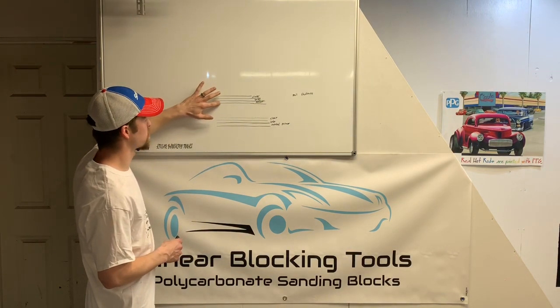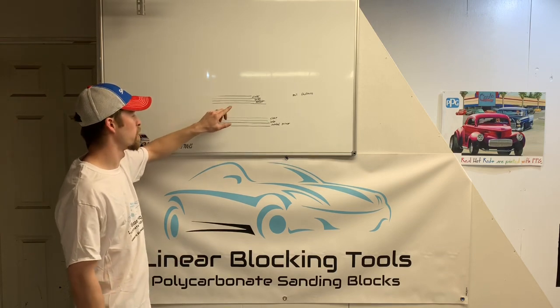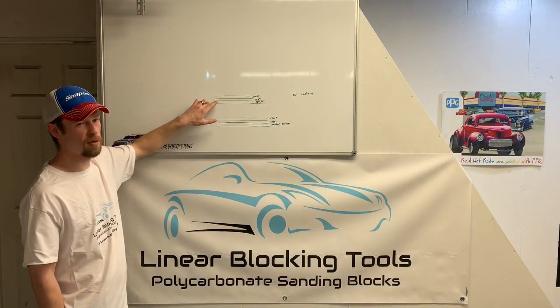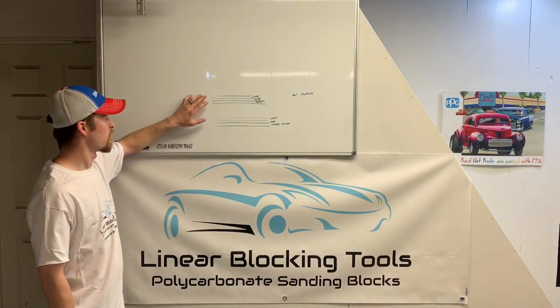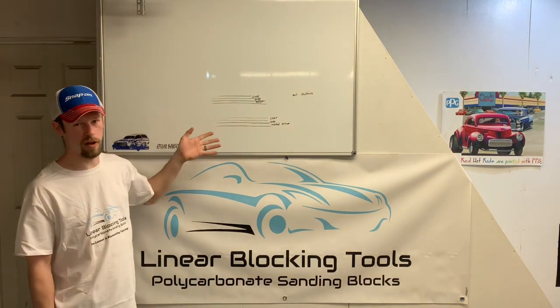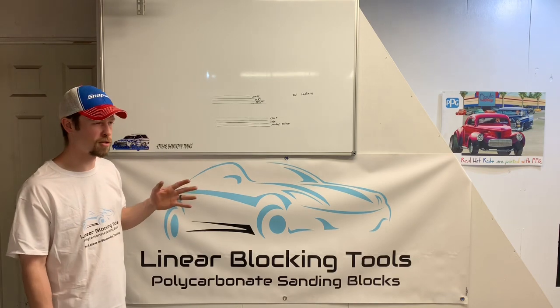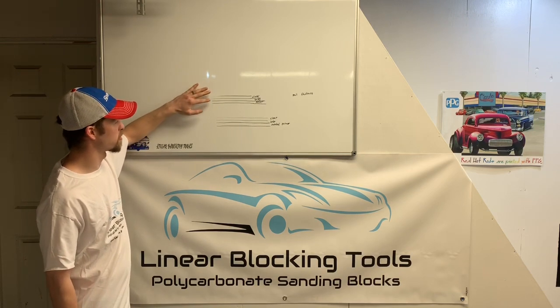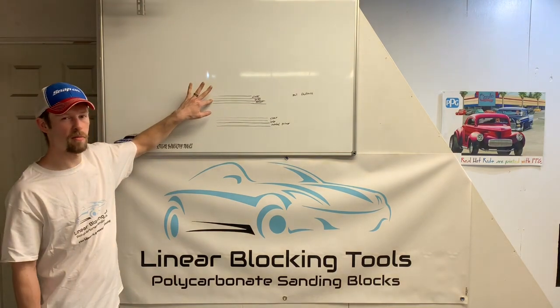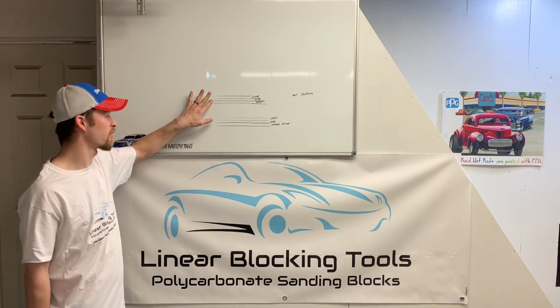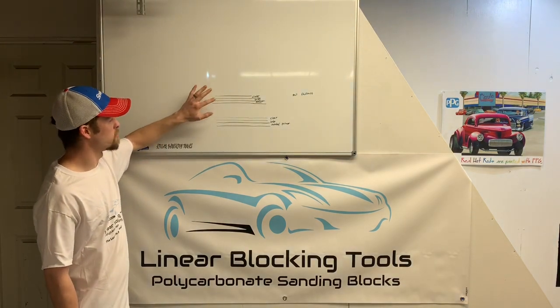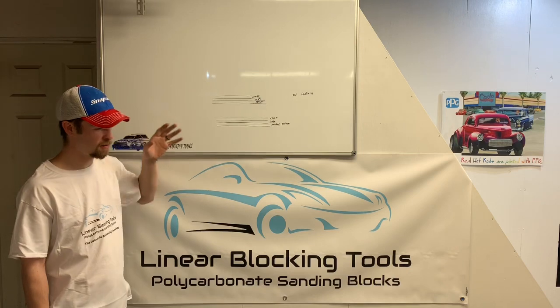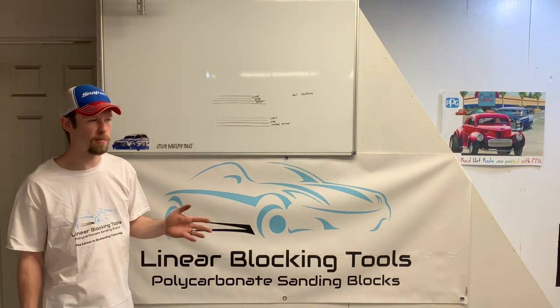With sealer down first, then base coat, then clear on top — when you use sealer, this is an activated product with isocyanates in it. This is the first step of your foundation. Then you use base coat over your sealer. With sealer you're going to use a value shade, most likely one through five or one through seven depending on your system. As you're painting, you're stacking these products on top of each other. Your base coat is probably not activated, though you can use an activator — we'll get into that in a minute.